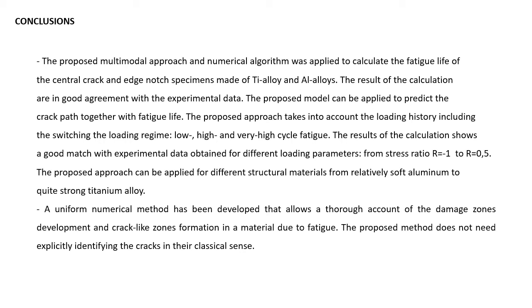And also a uniform numerical method has been developed that allows a thorough calculation of the damage zone development and crack-like defect formation in a material under cyclic loading. The proposed method does not need explicit identification of the crack in the classic sense.